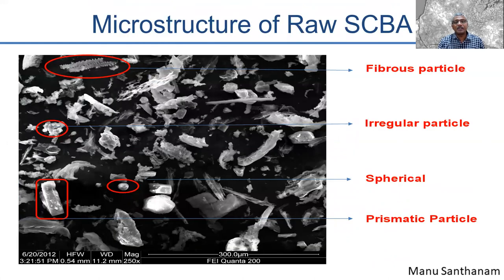So for that, first we tried to understand the microstructure of this raw bagasse ash as it is collected from the site. We went and collected bagasse ash from some sugarcane plants or sugar mills in the south of Tamil Nadu. And we then did a scanning electron microscopy study to try and understand the different morphologies that we can see in this material. You can see here that the material has a combination of fibrous particles, irregular shaped particles, and more regular prismatic or spherical particles. So obviously, when you start seeing prismatic or spherical, you know that there is some degree of shape that has been obtained by the material.